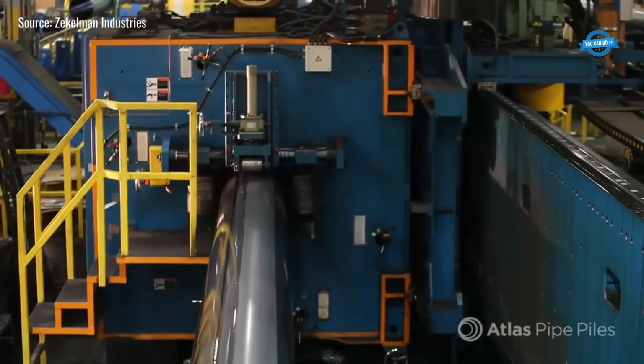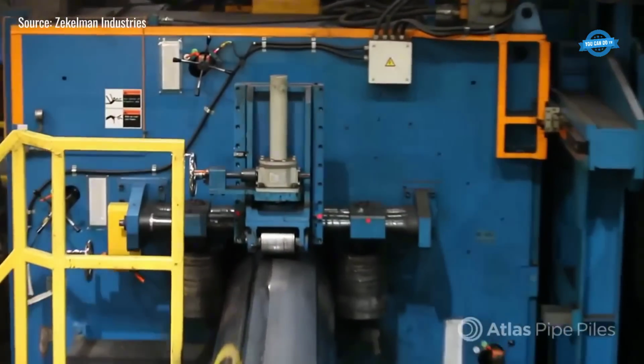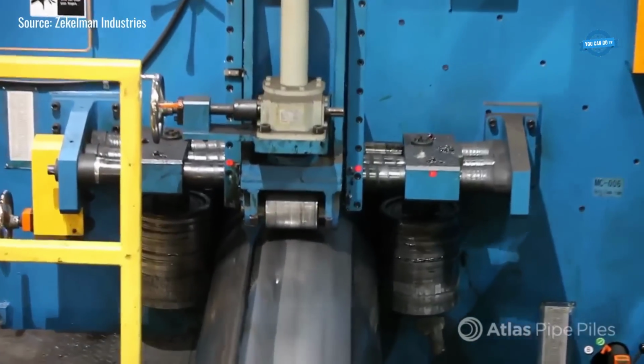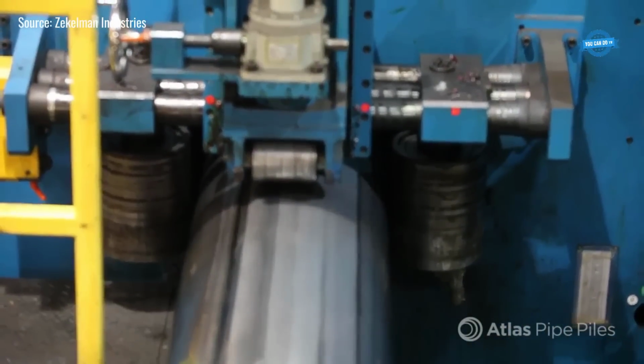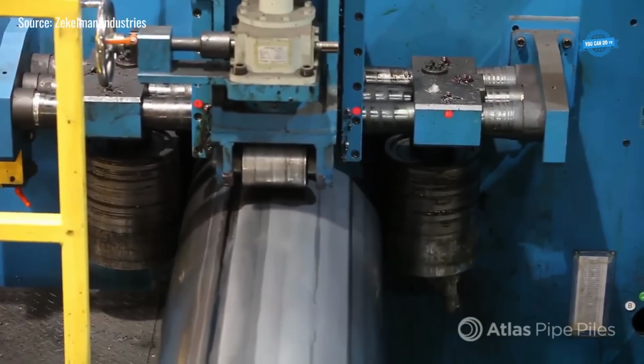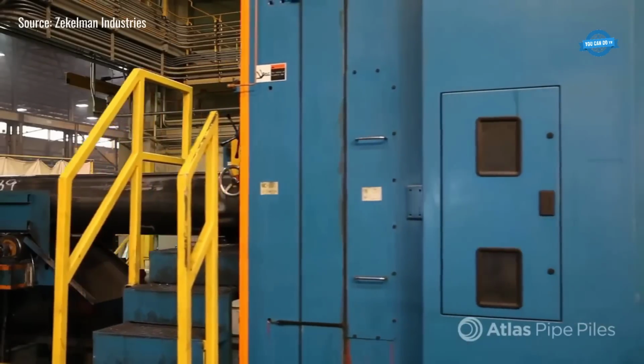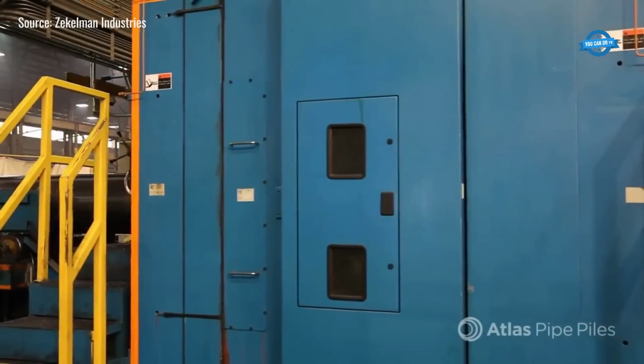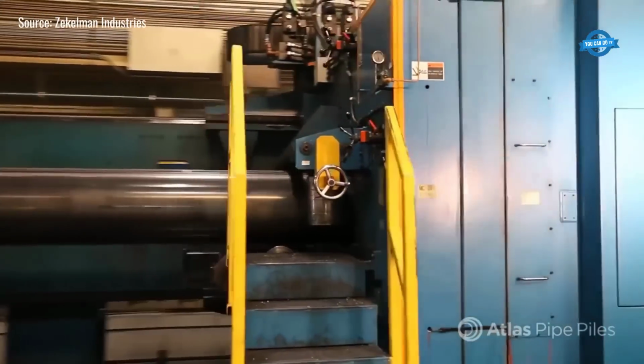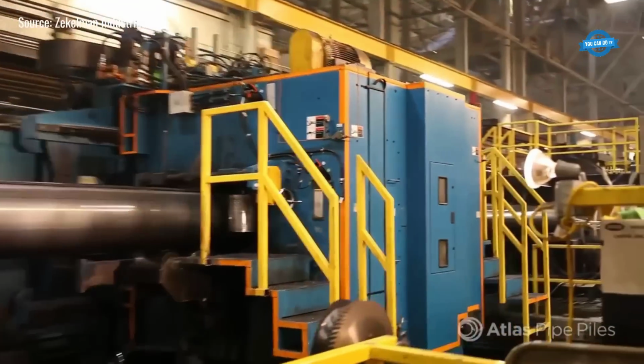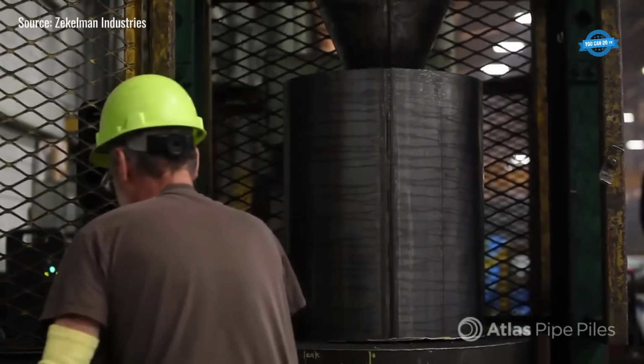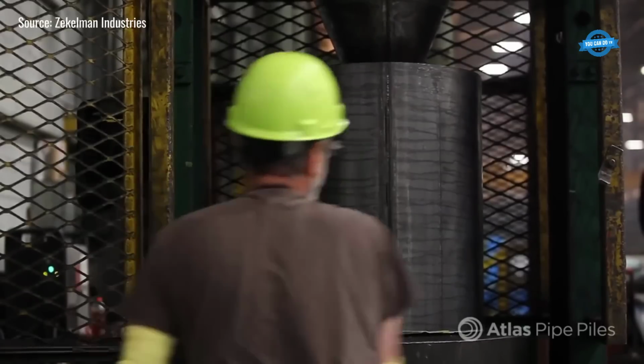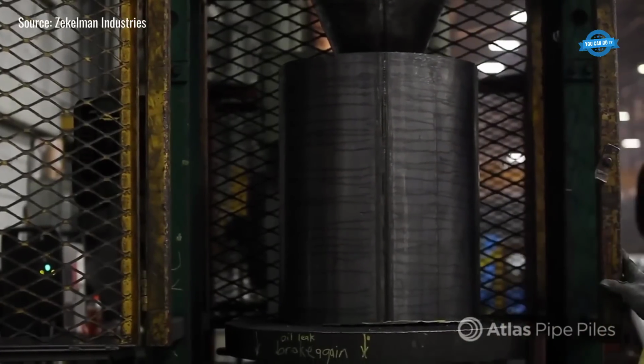Once welded, the pipe undergoes ultrasonic testing to verify weld integrity and detect any internal flaws. Defective sections are automatically removed, ensuring the highest quality standards. After testing, the pipe is gradually cooled using water and coolant to prevent thermal cracking. The Turk's heads then refine the pipe to its final size and provide a smooth surface finish.